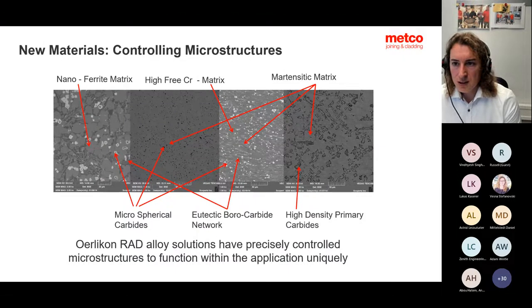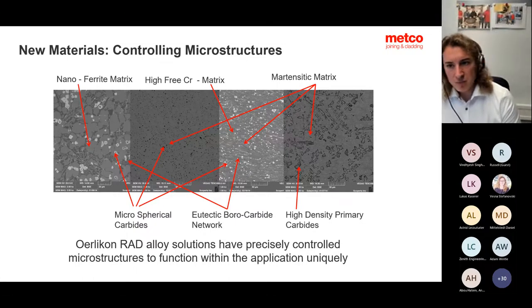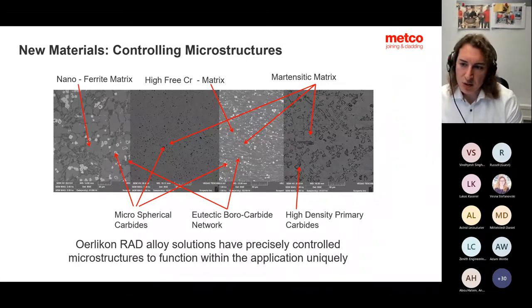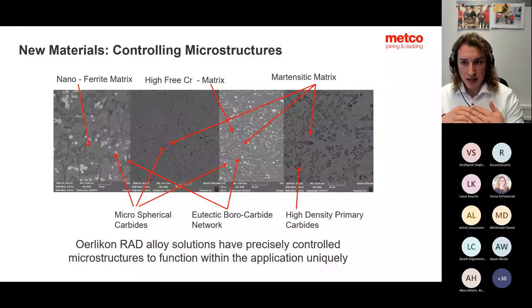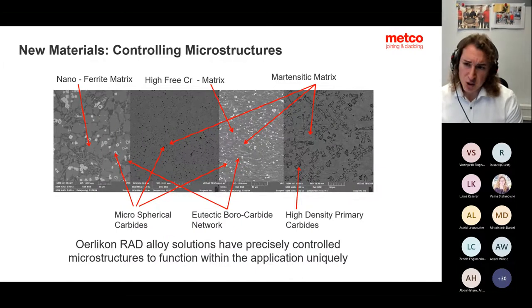So we not only interact with hardness. Best example, if I need corrosion protection, why not maintain a ferritic type of matrix with a high chrome content, which is extremely corrosion resistant, and then reinforce it with, for example, nano or submicro precipitation hardened carbides or carboborides, which do not have a dramatic effect on your hardness values, help you to keep the ferritic microstructure, do not cause a martensitic transformation, and at the same time, extremely increase your wear resistance. And this is also one of the aspects where rapid alloy development might have an advantage and help you to design materials and alloys from a different perspective.